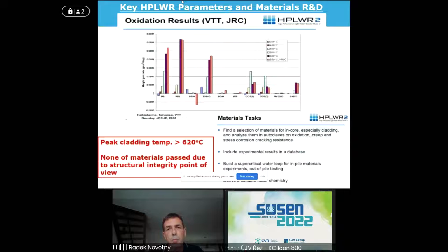I will also mention material R&D within HPLWR phase 2, and the reason is that it was a little bit of a failure. We didn't succeed in identifying the material for the fuel cladding. None of the materials passed all the criteria we determined before the project as criteria of success. The main problem was the cladding temperature due to deteriorated heat transfer, which was much higher than 620 degrees C, and we didn't find a material which would have enough strength or mechanical properties at this temperature and with the geometries used for the HPLWR concept.